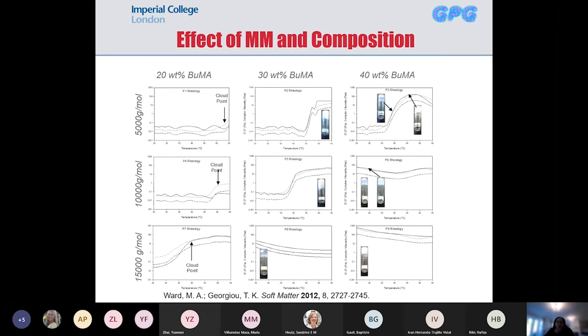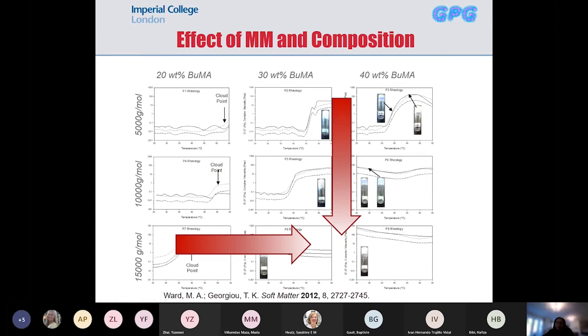Now, if we compare the effect of the molar mass and the composition, from left to right we're increasing the hydrophobic component. From top to bottom, we're increasing the molar mass. So we see two clear trends. As we increase both, we have the formation of gels more easily, but we have the undesirable effect of having gels at all temperatures. What we want is to have a solution at room temperature. So what we want is something in the middle. So essentially we want intermediate hydrophobic component and intermediate molar mass, for the ones we have tested, in order to have the desirable sol-gel transition.